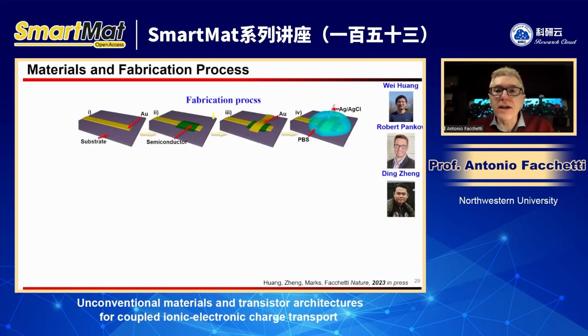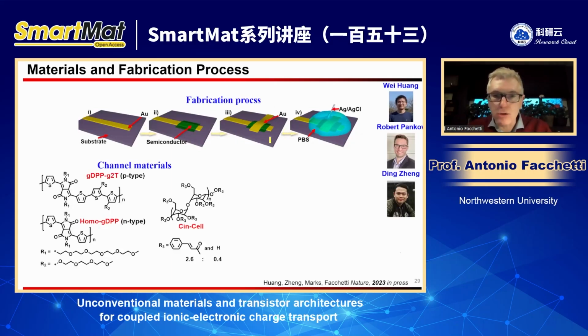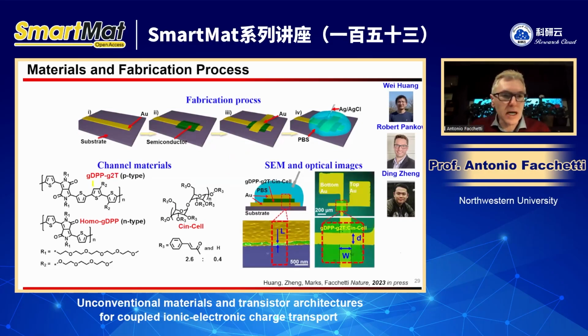And we have been able to make this device, which functions quite well. We use two polymers. This is an example of a P type, which we call gDPP-g2T, and this is an N type, which is a Homo-gDPP. The way we did it is blending this semiconductor with a little bit of this insulating polymer, which is a cellulosic polymer, which is very hydrophilic. And this is the cross-section of the device. This is the channel, and these are the gold and the gold, at the top and the bottom. And in between is the semiconductor. This is the top view of the device.